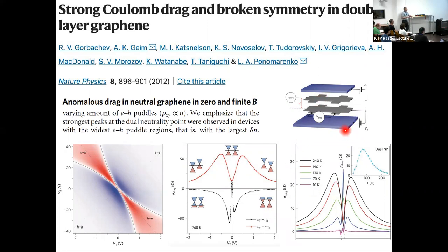First of all, because of the independent gate control, you have sort of four options. You can consider drag between electron-electron, hole-hole, electron-hole, hole-electron, depending on what you do. They found, first of all, that it's non-symmetric. And secondly, I think the most astonishing observation is that when you go to the double charge neutrality, meaning that each layer is at charge neutrality, they found a finite drag resistance. Then if you are in the electron-electron or hole-hole part, it starts to decrease, changes sign, and then dies out at high densities. And if you are electron-hole or hole-electron, it goes up and also dies at higher densities. The peak value of the drag resistance at charge neutrality has quite a complex temperature dependence and is non-monotonic. It rises as a function of temperature and then dies out at higher temperatures. All right.